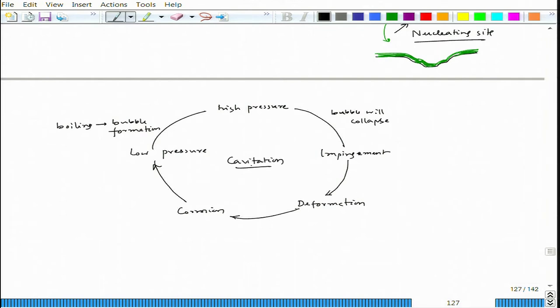So, this is in case of a non-passivating metal. If it is a passivating metal, then when the impingement happens, instead of deformation, the passive layer breaks. Okay. Then when the passive layer breaks, corrosion happens, that corrosion leads to formation of a passive layer, and then again low pressure happens, boiling, bubble formation, and the cycle will move on. So, this is basically a typical cycle of cavitation.